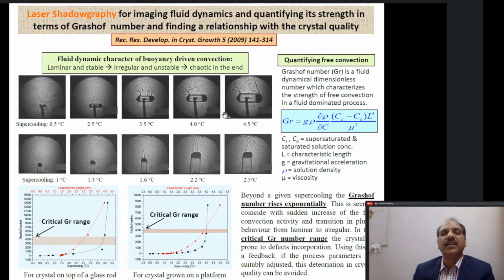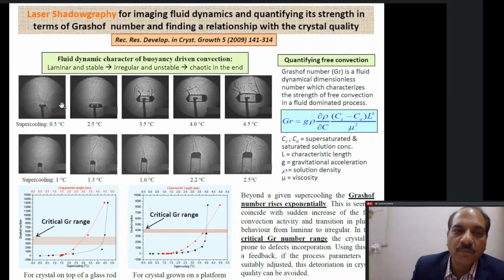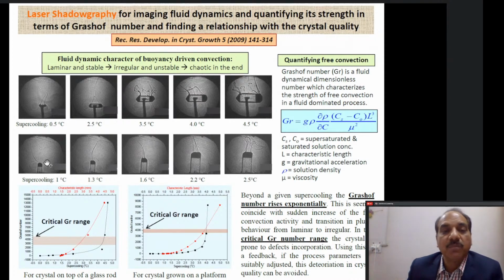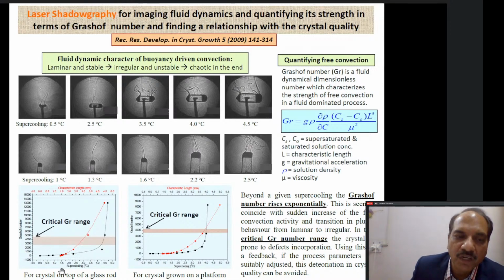So these are 2 different experiments which have been done, in which one crystal is hanging on top of a capillary tube, and in the other, the crystal is grown on a platform. The rapid growth technology of Professor Zaitseva of Lawrence Livermore, that experiment was simulated here, and we were able to calculate Grashof numbers for both these experiments. What we found was this: this is for the crystal on top of a glass rod or a capillary, and this is the crystal grown on a platform.